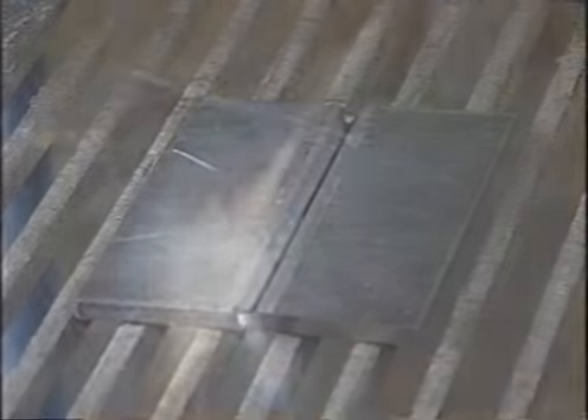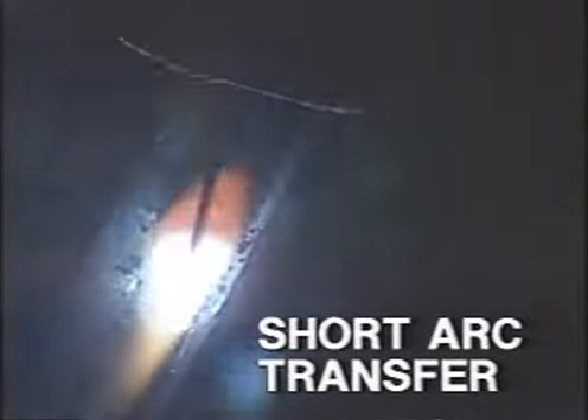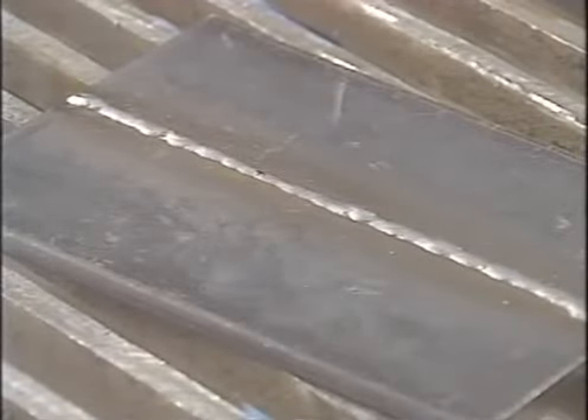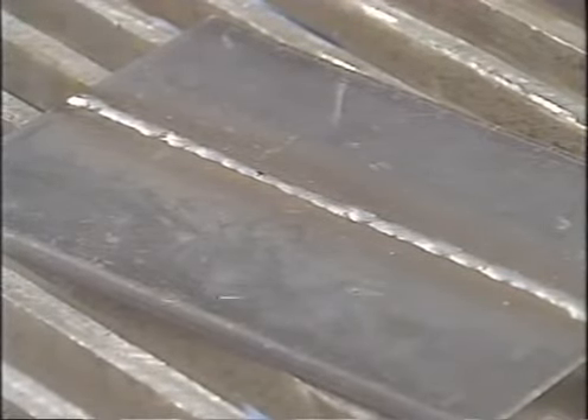After tacking, angle the gun at approximately 45 degrees in the direction of welding and deposit the root run using the short arc transfer mode. Subsequent runs are deposited using the circular technique until the weld is completed. The final runs are called capping runs. To seal the joint, deposit a weld bead along the bottom of the root weld.